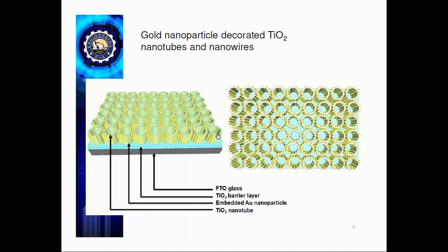Okay, so now coming to the topic of plasmon-enhanced SERS sensing, it's very well known in the SERS field that the electromagnetic enhancement factor that you get from a localized surface plasmon resonance is the fourth power of the field enhancement for Raman spectrum, which means by introducing a plasmon resonance, in theory, you can achieve a 10,000 times higher signal. So that's the principle, and that is why a lot of groups around the world have been trying to make plasmonic nanocomposites. And the other reason being titanium dioxide is a particularly robust sensor on which naturally a lot of small molecules tend to adsorb and form self-assembled monolayers. So the combination is expected to be very powerful, but that's the theory.